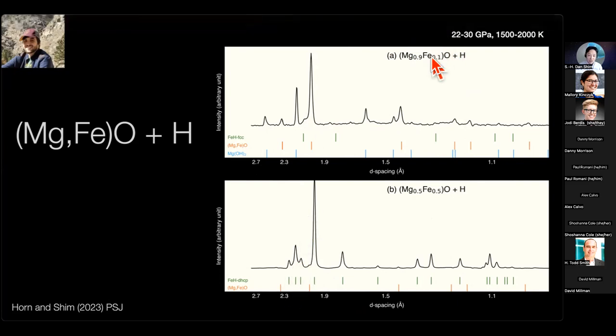We start with MgFe oxide with hydrogen, with different amounts of iron in this case, to the conditions where these materials are known to undergo partial melting. After the heating, we find that an iron hydrogen alloy forms, which means that we reduce Fe2+ in this structure and turn it into iron metal and then alloy with hydrogen. And then we also identify the peaks from Mg(OH)2, which is magnesium hydroxide.